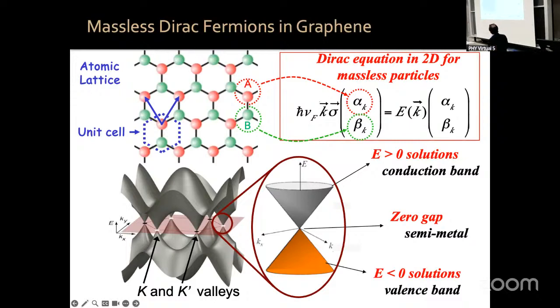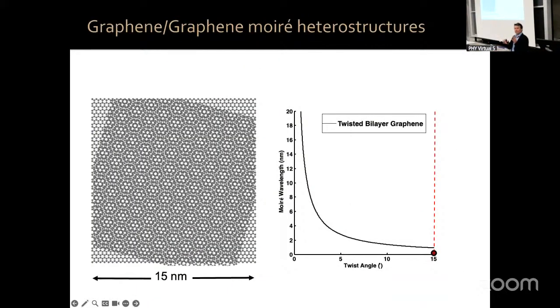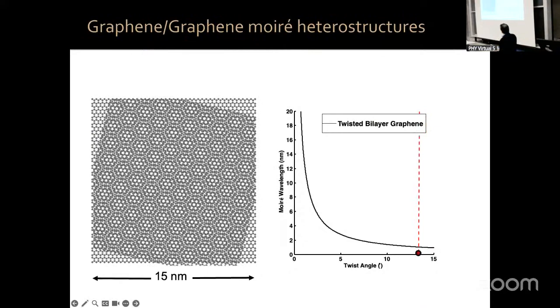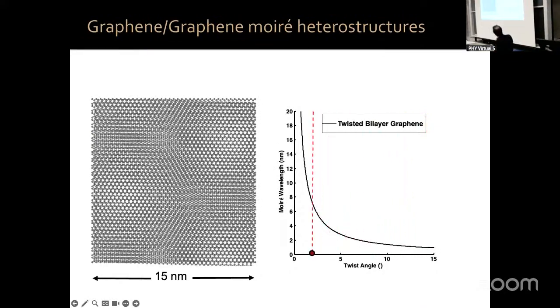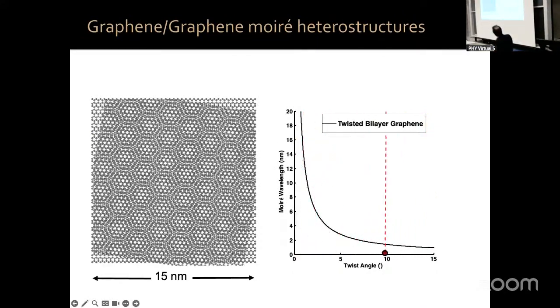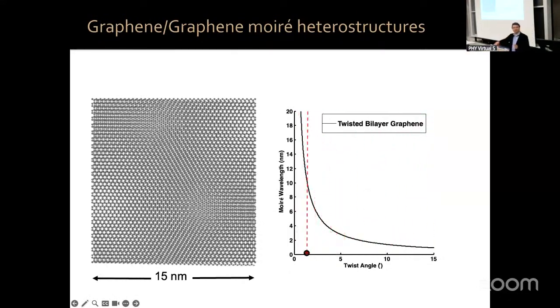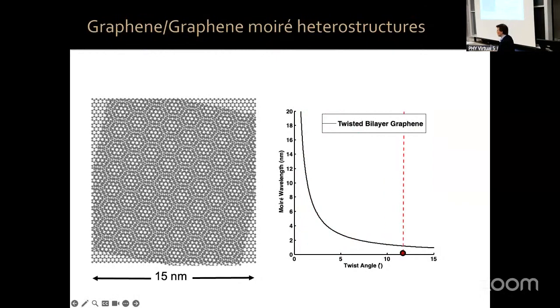What happens if you put two sheets of graphene on top of each other and rotate them? A moiré pattern forms, where the moiré wavelength, the distance between the soccer balls you see on the screen, is roughly inversely proportional to the twist angle, at least at small twist angles.